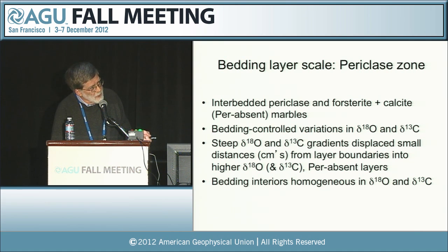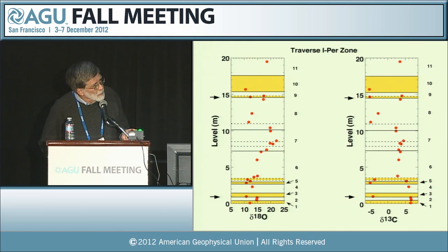And there'll be steep gradients that are coherent at these boundaries. And the bedding interiors are pretty homogeneous in their oxygen and carbon isotopic compositions. That implies that on the scale of an individual bed, the permeability is pretty constant. So let me just go quickly through a few of these plots.